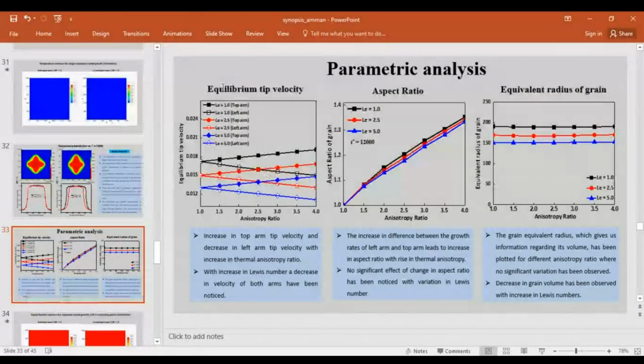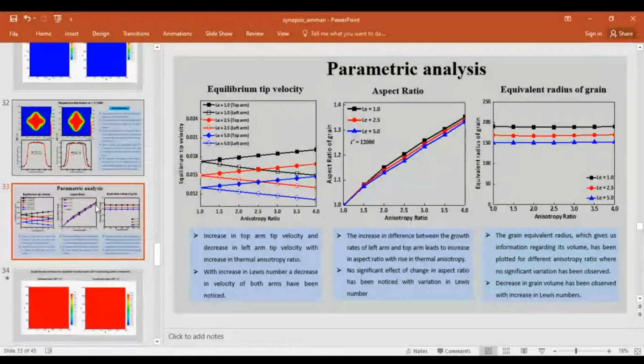This is the parametric analysis carried out on equilibrium tip velocity, aspect ratio, and equivalent radius of the grain. We can see the top arm moves at a faster rate for the anisotropic crystal, and with the increase in Lewis number, there is a decrease in velocity of both arms. For aspect ratio with the anisotropy ratio, it has been observed that the increase in difference between the growth rates of the left and top arm leads to an increase in aspect ratio. For equivalent radius, which gives information on the overall volume of the grain, it has been plotted for different anisotropy ratios.